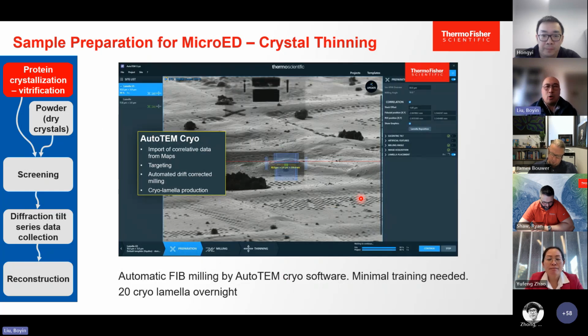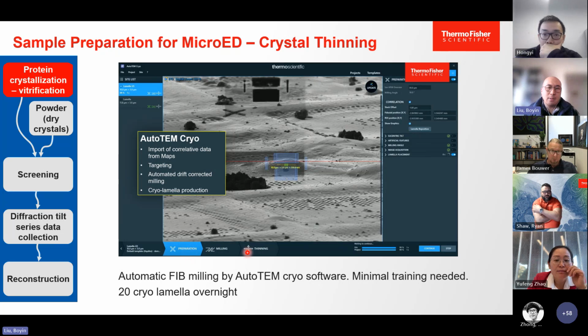And we actually have automation software to do this work. It's called AutoTEM Cryo. It has been used by the cryotomography community for a couple of years, and we have very good feedback. You can see that in the software you have three steps. The preparation step is for finding eucentric height and milling angle automatically, the milling step is for rough milling, and the medium milling and thinning step is for polishing. The software is on the right-hand side, and you can see there's a recipe there. As long as you have a good recipe, it's a completely walk-away acquisition.